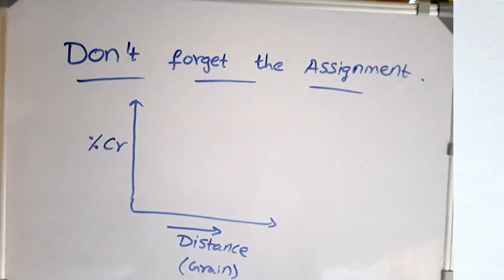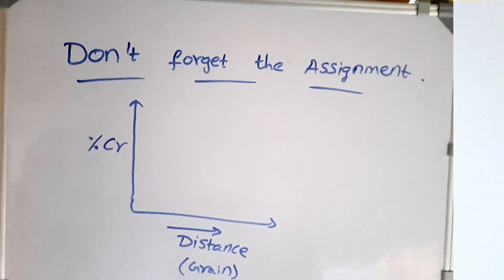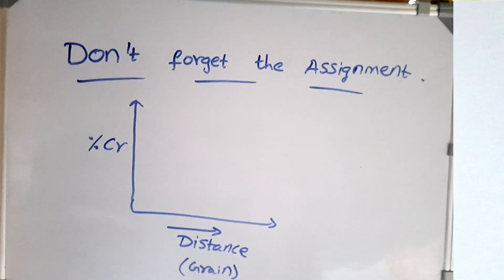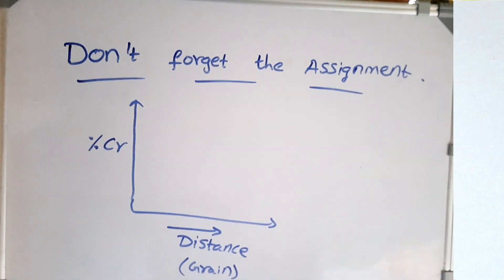Let's have a recap. Sensitization of stainless steel is the formation of chromium carbide at the grain boundaries. Intergranular cracking: because of sensitization the grain boundary region becomes brittle and cracks propagate between the grains. Stabilization of stainless steel refers to all the methods by which we avoid formation of chromium carbide. Weld decay is sensitization occurring during welding of stainless steel. Knife line attack is sensitization occurring in stabilized stainless steel. Stress corrosion cracking is failure occurring because of the combination of stress and corrosion.